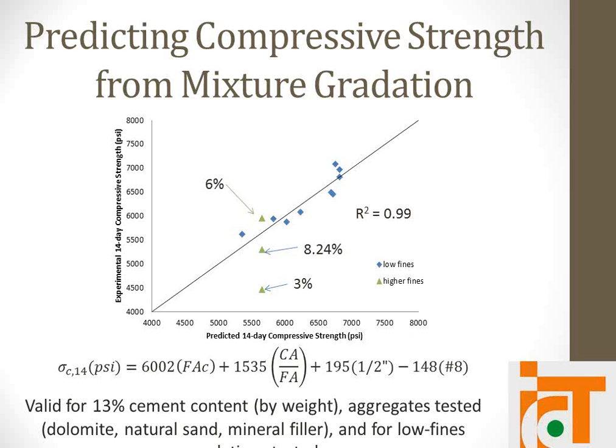So then, using the gradation properties and the Bailey method, the FAC ratio from the Bailey method, the coarse to fine aggregate ratio, which is one of the things we wanted to look at, as well as percent retained on 1/2 inch and number 8. A regression was developed for the low fines mixes in the blue there. Found good agreement. There's a caveat that it's only for a certain cement content and just for those aggregates that were used. And then when comparing that to these higher fines contents, there's basically no agreement. That's an area for future research, to see why these fines contents were so different.